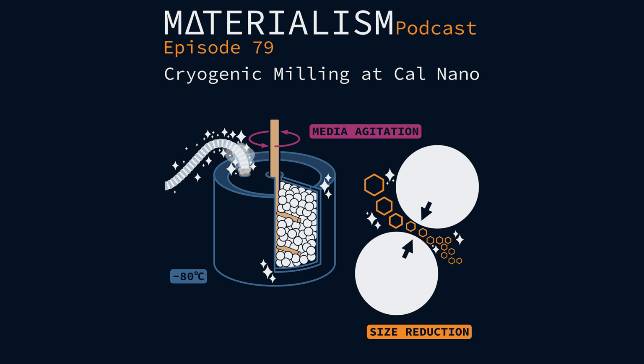But you still see the tungsten carbide left over in your signal afterwards. It's almost inevitable to see some sort of small contamination. I imagine you get some cobalt, too. Yeah, oh yeah, because it's not pure. It's not the pure ceramic, right? Yep. You want the toughness, and so they add a little bit of cobalt there.